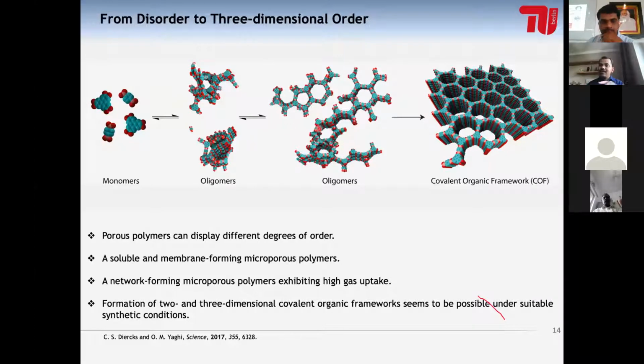So how can we create these materials error-free, and then call them covalent organic frameworks without any defects inside? To do that, we have to use different reactions which are reversible. What reversibility can do is, for example, if there are a lot of errors in this material, they can be corrected after going back and forth. If there is an error, this molecule can be detached, go back to the original state, and then come back and put itself exactly where it has to be, and then form bigger oligomers before it forms perfectly ordered crystalline materials which have high thermal and chemical stability as well.